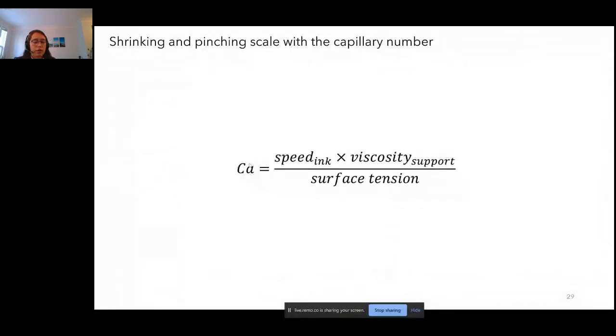So in order to map these oil-based inks onto some sort of constitutive relationship that tells us how we can balance all of our properties, we can use the capillary number. So that's the speed of the ink times the viscosity of the support divided by the surface tension. So that capillary number is telling us how we need to balance the viscous dissipation in this system against surface tension.